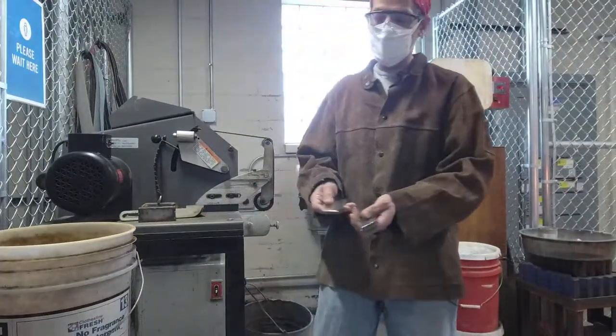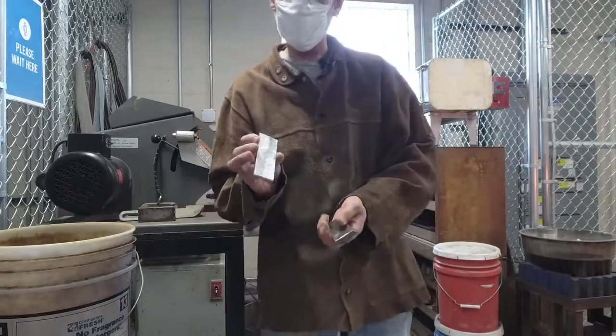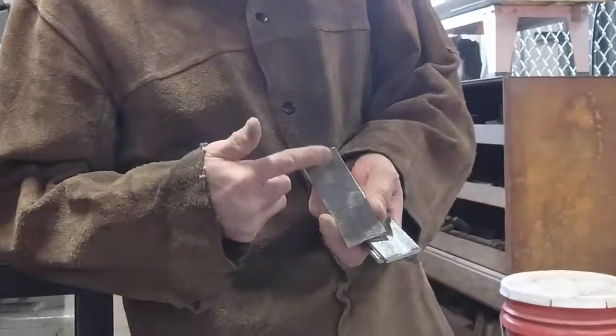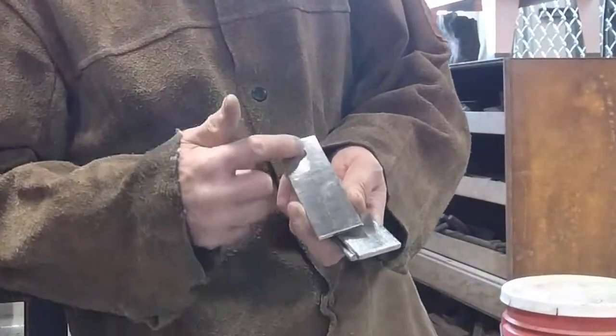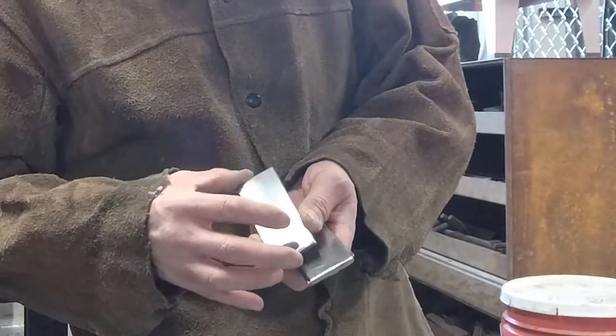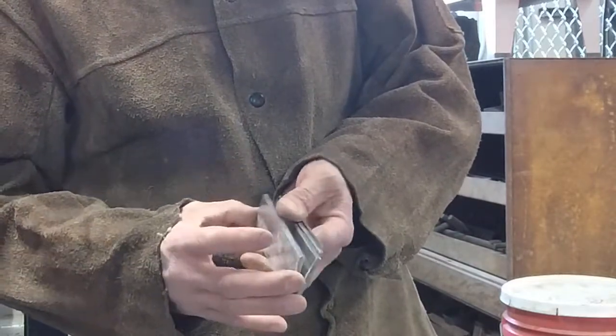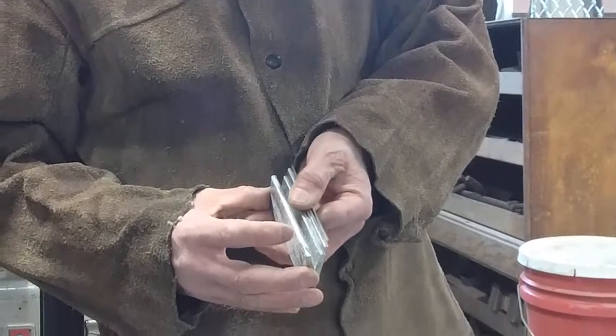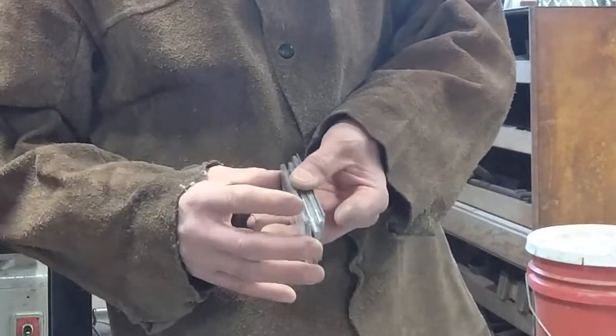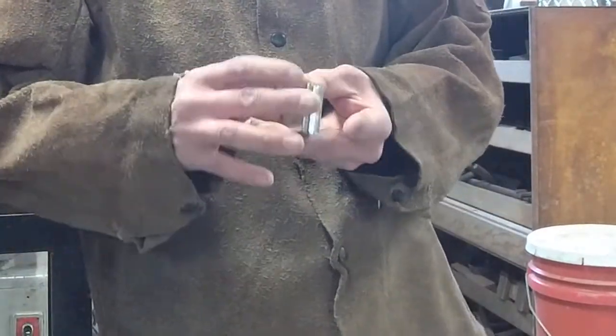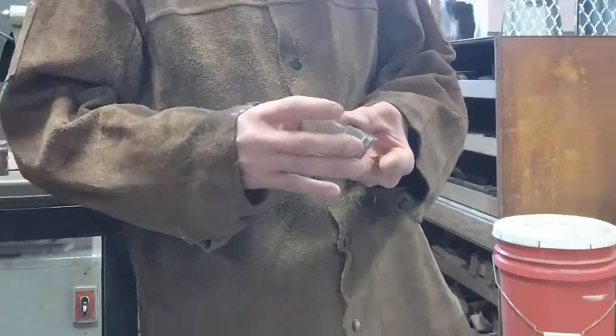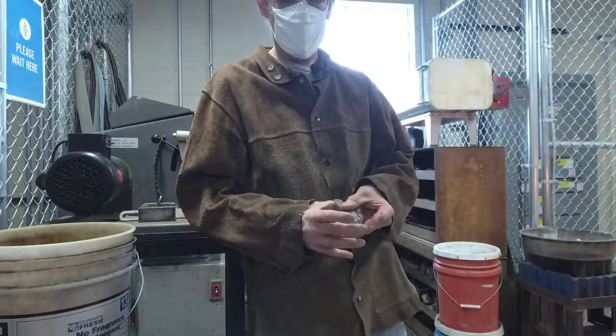Okay, the other layers I've already cleaned. It's very important to have clean steel before you start. If you don't, dirt, oxide, other junk basically can get trapped between the layers. It causes what we call a delamination, just a bad spot.